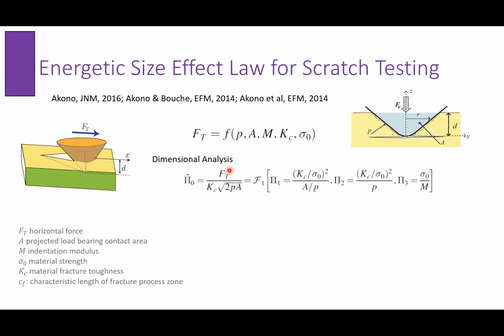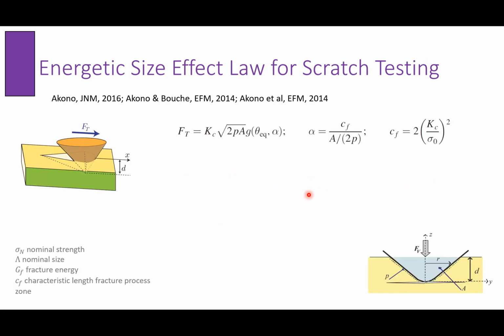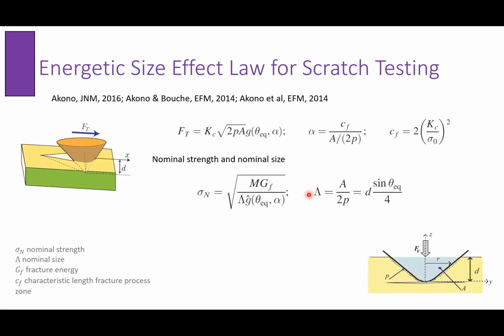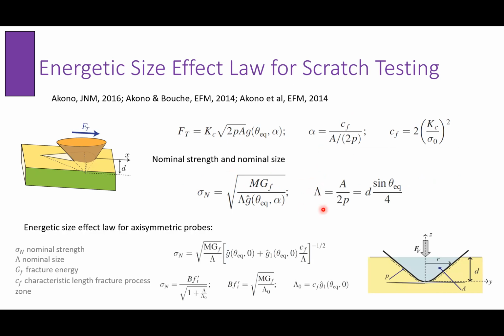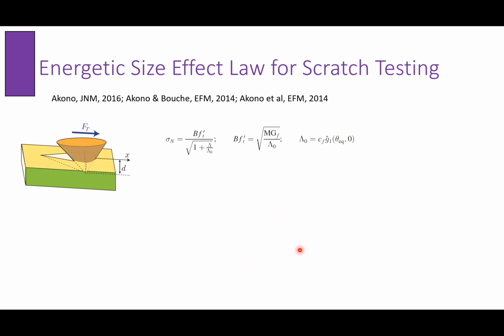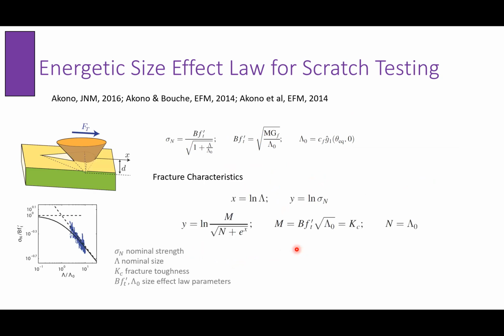So we have the LEFM solution with the dimensional analysis, where this is going to add a new functional, and the value of this functional is going to be equal to 1 when we are in the ideal case of a purely brittle process. So what we can do is use a Taylor expansion around the nominal value, and based on that Taylor expansion, we're going to have the energetic size effect law in this case. What was really good is that we were able to also validate that energetic size effect law on shale, and also organic-rich shale.